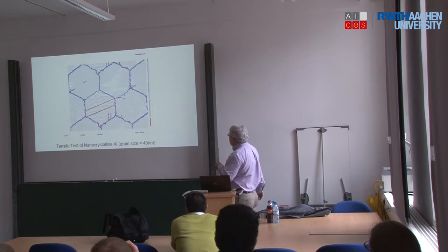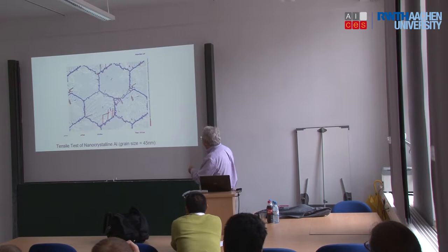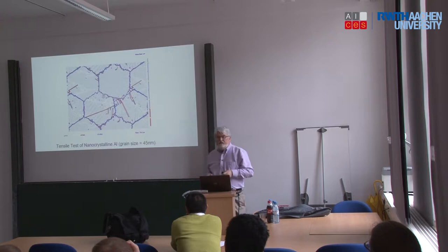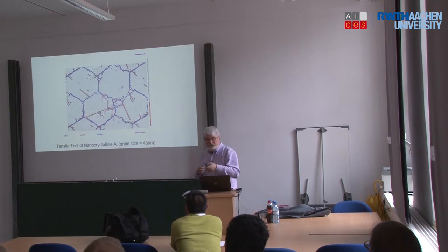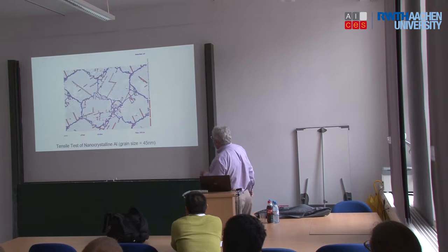But what you're seeing here is the generation of dislocations crossing stacking faults. You're forming locks. And now over this region, we're forming new grains. So what we're seeing here is the mechanical evolution of a system at the atomic level. This is the sort of question that molecular dynamics is very, very good at answering. And as I say, this is quite an old simulation, so we can actually do better now. But this does really tell the story of what's going on.